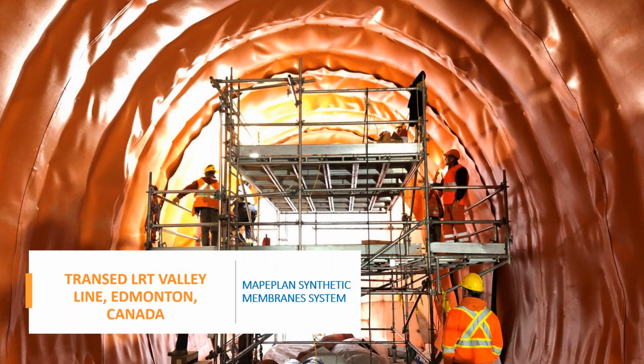In the same project, here is another photo where people start applying membrane to the arch of the tunnel. We can see here we start to fix the membrane using a fixing disc to the substrate. We see the overlap, and we also see people testing this overlap using an air pressure test.